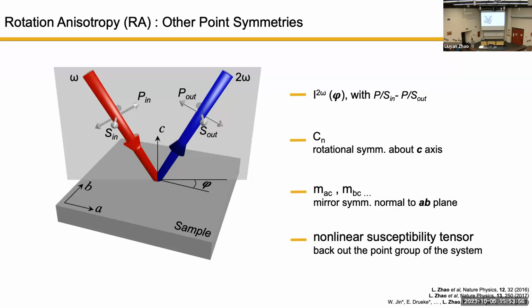I can choose one or all 4 of the channels, and record the SHG intensity as a function of the angle between the crystal axis and the scattering plane. So in a real experiment, I essentially just rotate the beam around the sample and keep on recording my SHG signal. Then if I look at this data set, you can directly visualize whether my data has rotational symmetry, or a mirror, or any other operations. So this kind of measurement directly gives you the visualization of symmetries, for example, rotation, mirror, and others.